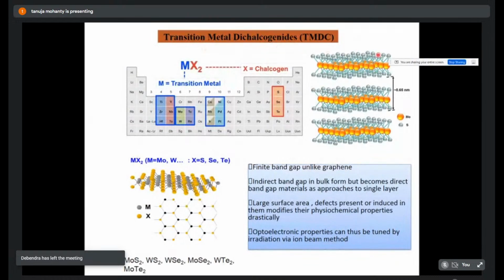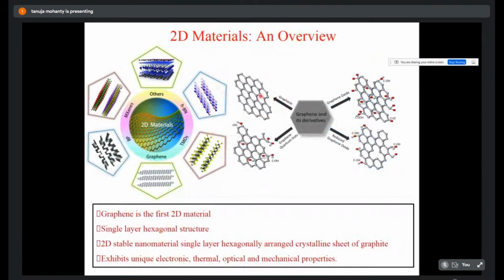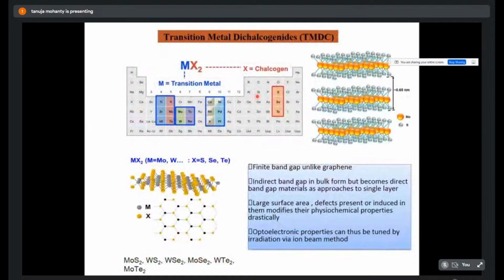So then it comes to what is 2D. One is the graphene, as I said, where you have this single layer and it is like a zero band gap material. Then it comes to transition metal dichalcogenides. Here the transition metal in the periodic table, and dichalcogenides come here. So the combination from here to here gives you the dichalcogenides. Why dichalcogenides? It is not a single layer, rather one layer of M between two layers of X, and the complete unit is called one layer. Normally the interlayer distance in graphene and those things starts with 1 nanometer, or 0.65 nanometer in the case of this MX2. This transition metal M can be molybdenum or tungsten, and X is not oxygen but sulfur, selenium, tellurium, the chalcogenides. So these are the materials which are well studied.